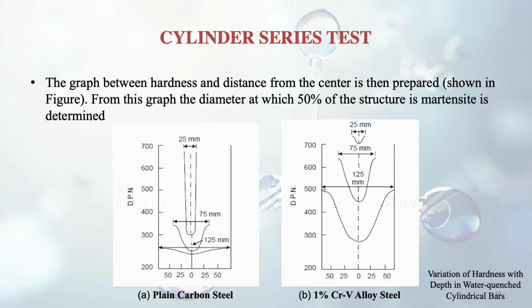From this graph, the diameter at which 50% of the structure is martensite is determined. At the bottom, around 250 on the hardness scale, a 125 millimeter cylindrical hardness can be achieved, whereas around 350 on the hardness scale it is only 75 millimeter, and at 700 on the hardness scale it is only around 25 millimeter. So martensite is around 700 on the hardness number, and a cylinder of around 25 millimeter diameter can be turned into 50% martensite. This is what is signified in this figure.